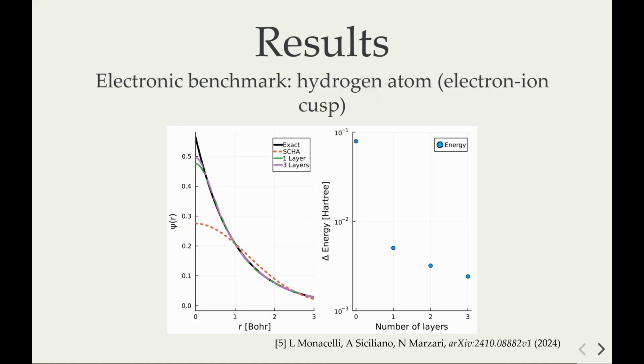Now let's see how this performs with electrons. Here is the hydrogen atom, a very simple system where we know the solution analytically. But the problem is that the hydrogen atom has an electron-ion cusp, and a Gaussian distribution cannot capture this cusp. With this very simple transformation I showed you before, even with few layers, we do better and better, and we improve the quality of energy. Indeed, we would need an ad hoc transformation to fully tackle this, but this is a very good sign already.